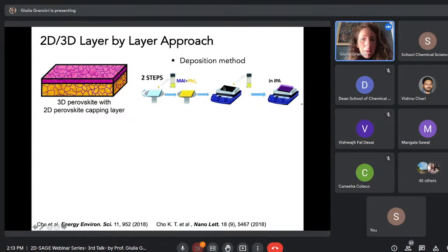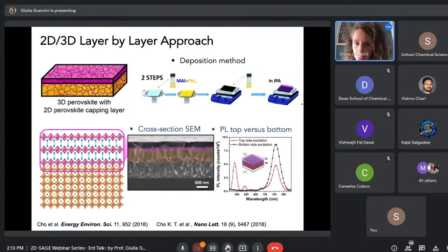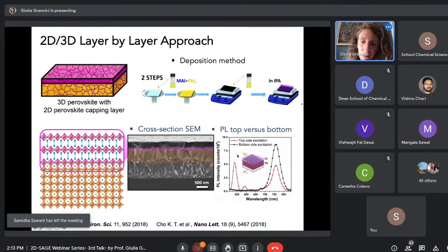You create, by a two-step deposition method, first the 3D perovskite with an excess of lead iodide, and then you deposit the precursors, the organic cations of the 2D perovskites, on top, which can react in situ with the excess of the lead iodide to form this very, very thin layer on top, you can see it here, of 2D perovskites. The 2D perovskites have a wider band gap with respect to the 3D, so that you see from PL, exciting from the top side, that the emission at 500 nanometer is a clear signature of the presence of the 2D perovskites.